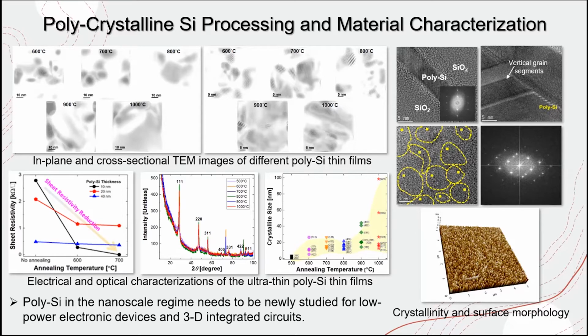This crystallite is too small for us to call it a grain, much smaller than a grain. So the crystallite size is 10 to 20 nanometers. In the past, polysilicon electronics were prevalent, particularly in display TFT technologies, but these days polycrystalline silicon is gaining increasing demand and interest for three-dimensional VLSI having different layers with different functions.